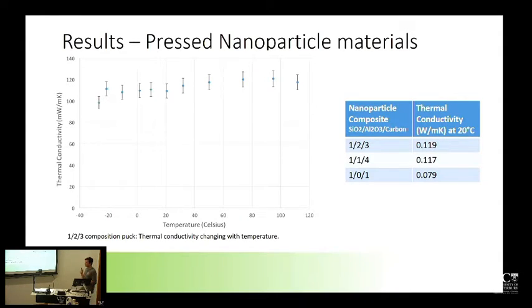So these are the results that I got off the nanoparticle pucks, and I don't think Bob has actually seen this graph yet. But this was a sweep that I did from negative 35, I believe, up to 100 degrees. Above 100 degrees, one of the adhesives I'm using starts to burn, so I stopped taking it above there.